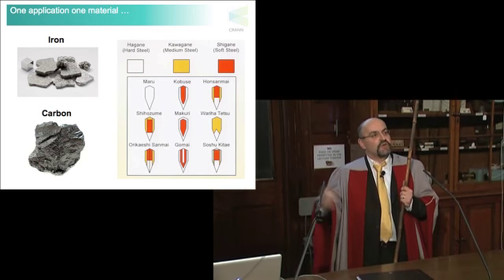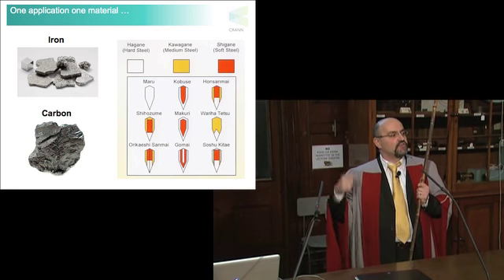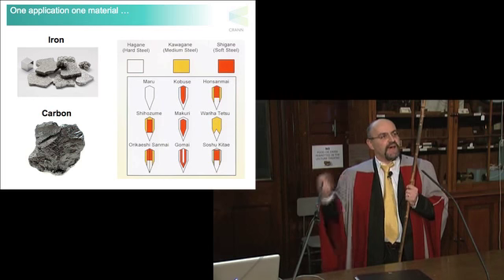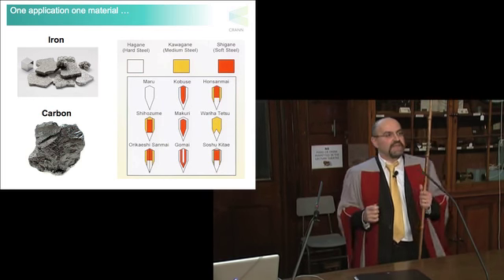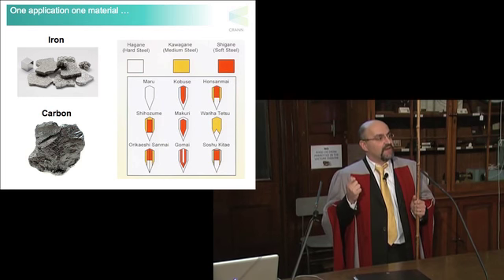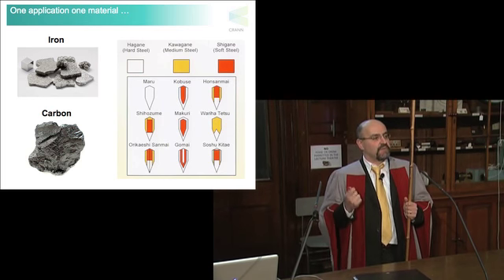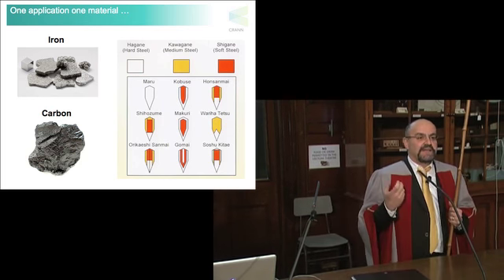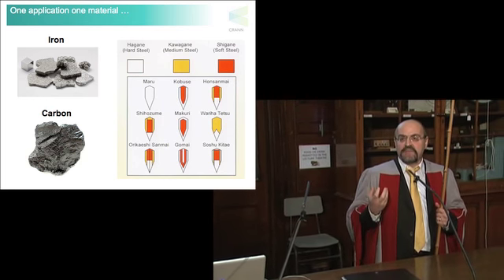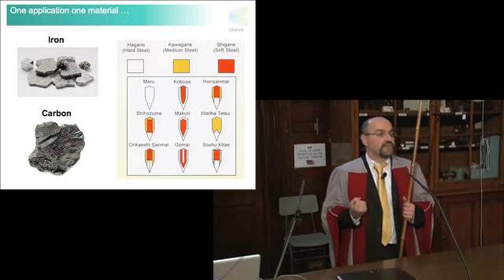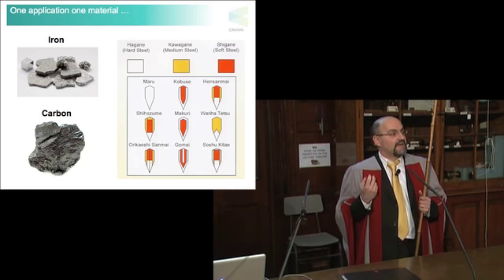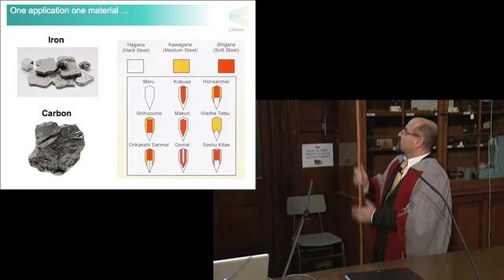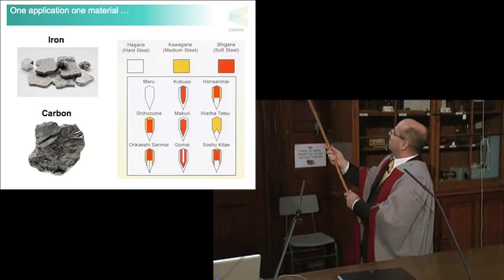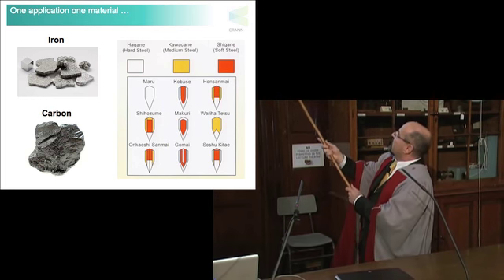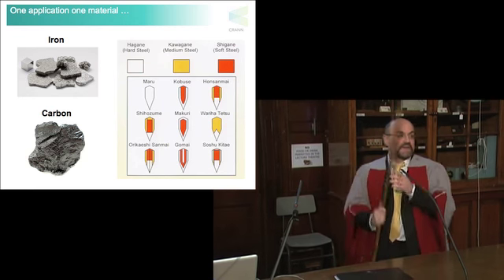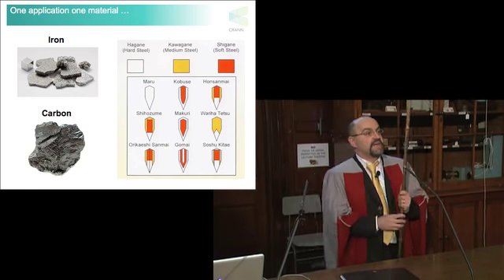Iron, when you dissolve carbon into iron, becomes harder and harder. You can actually do too much, but the more carbon you can put in, the harder it becomes. And when steel is very hard, you can cut it very sharp, but it's very brittle, so it can break. However, when steel is less hard, it is much more resistant to fracture, but cannot be sharpened, and your sword is not going to cut after a while. So what this Japanese craftsman managed to do was to essentially compose a sword. So this is a cross-section of a sword, combining hard steel and soft steel in a very, very specific way.